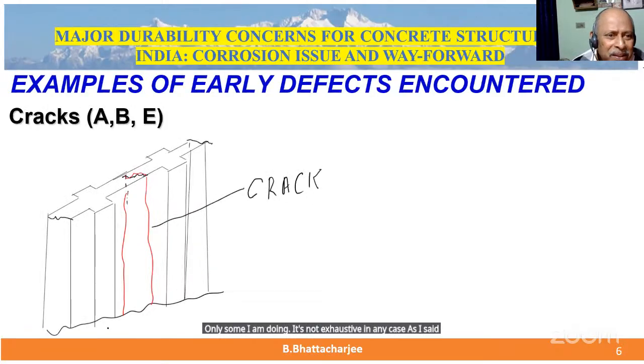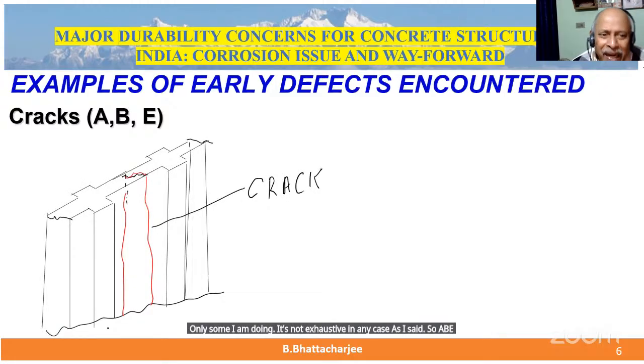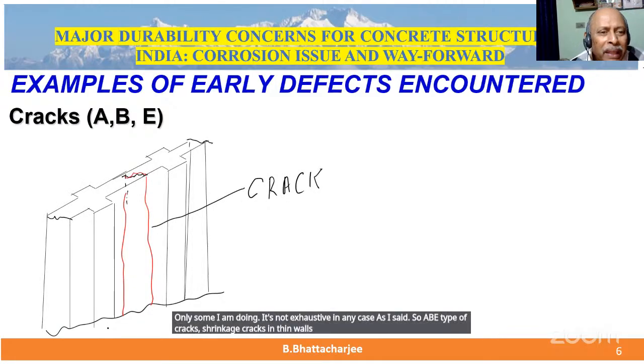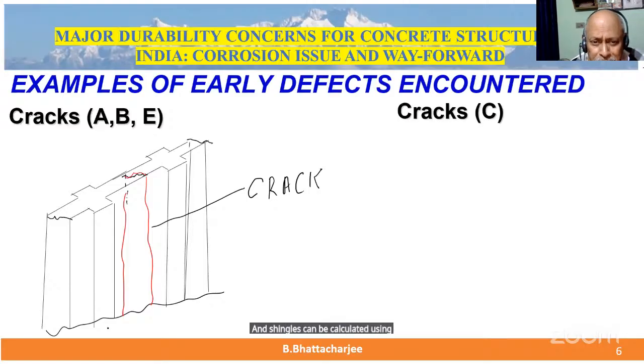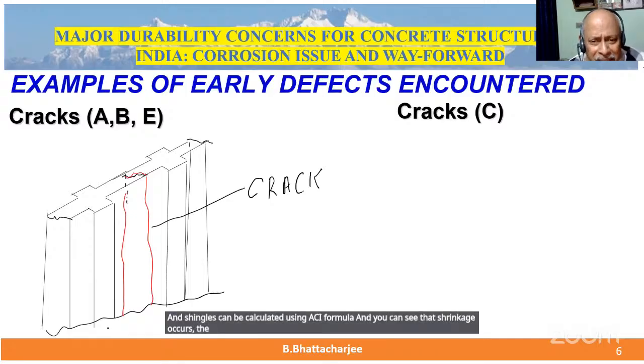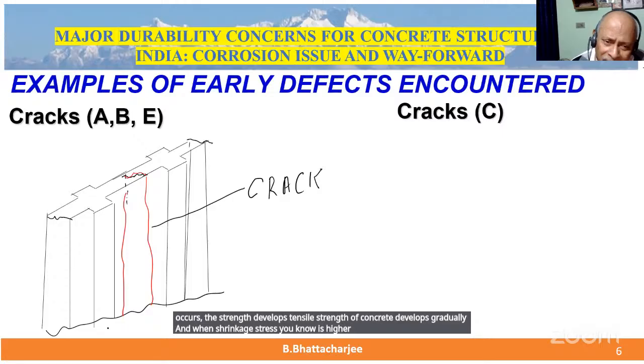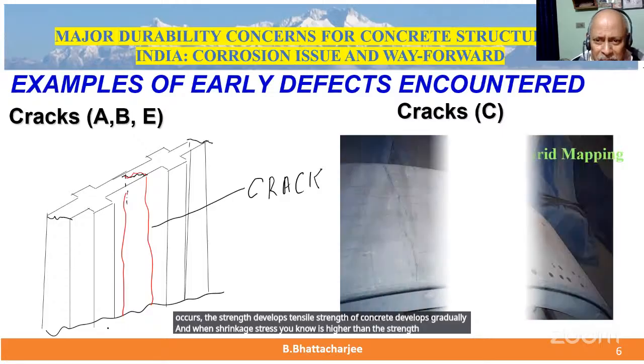So this type of cracks, shrinkage cracks in thin walls, they look like this. If there are buttresses, they will be between the buttresses because the wall will try to shrink. And shrinkage can be calculated using the ACI formula. You can see that as shrinkage occurs, the tensile strength of concrete develops gradually. And when shrinkage stress is higher than the strength, cracks would come. So this can be done.